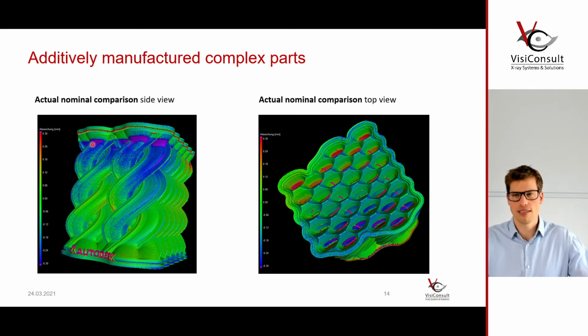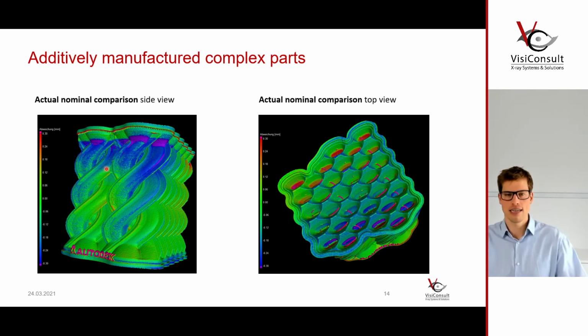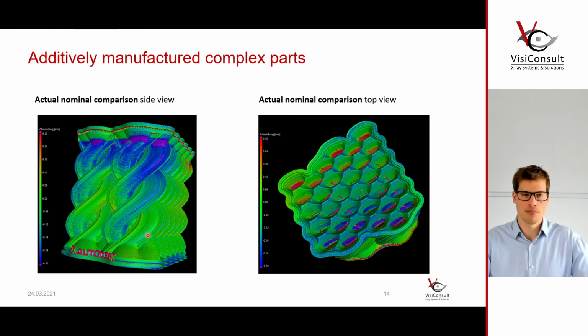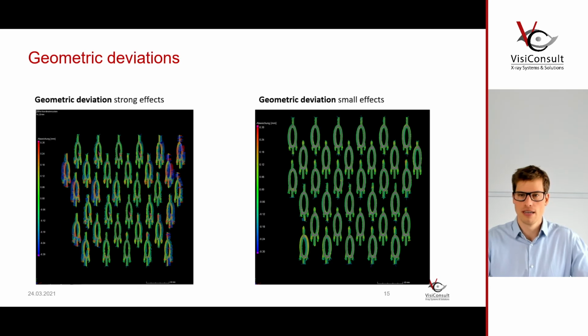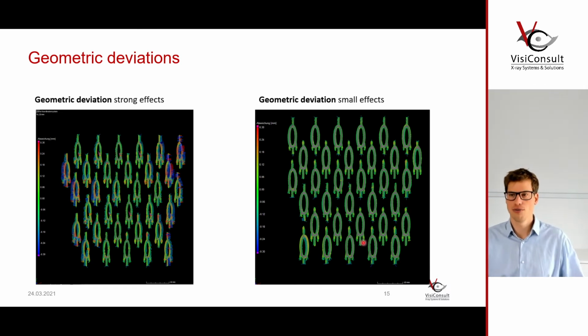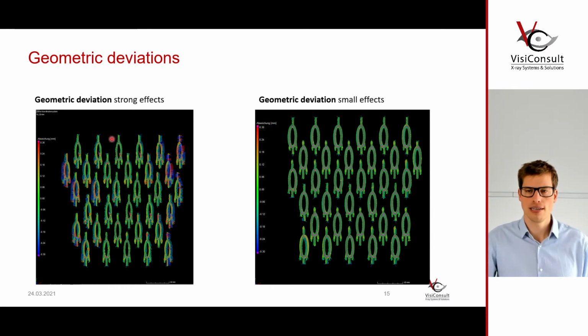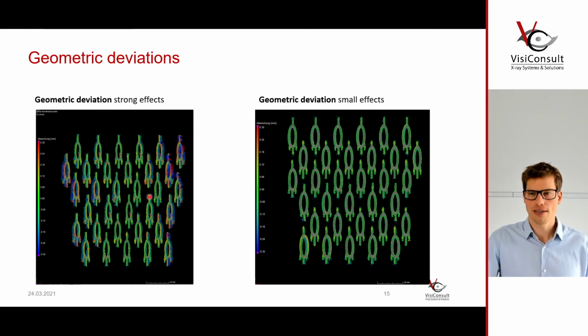But what's more interesting is up here, because you have a skewed part. It kind of tilts into the inside, and this can be a problem in terms of tolerances, in terms of manufacturing, but also in terms of functionality. So when we look at the cross section, you can see that on the bottom you don't have this. So you have a very nice uniform design structure, and the further you go up in the part, this is from one of the top layers, you see a big skewing in this area. Well, you see deviations in most of the part.